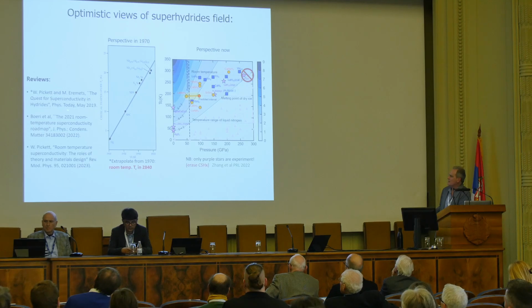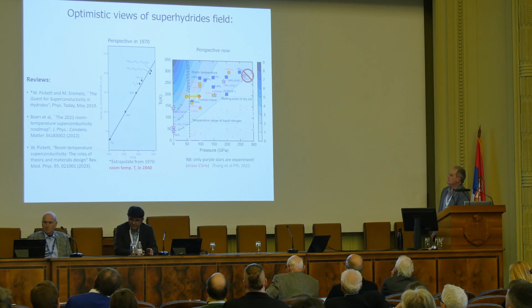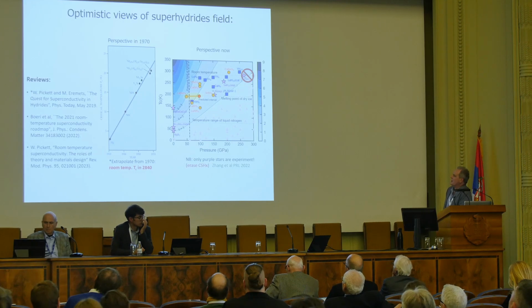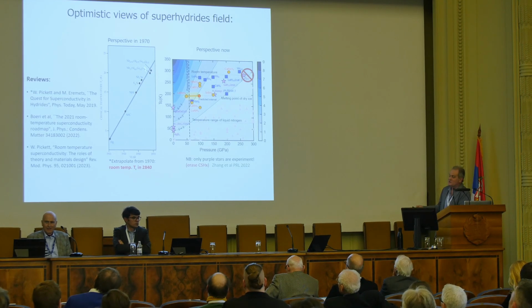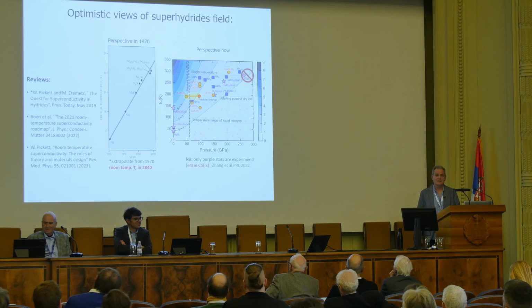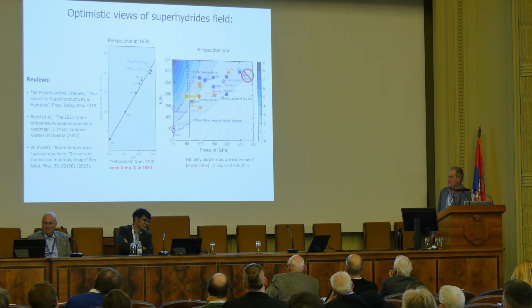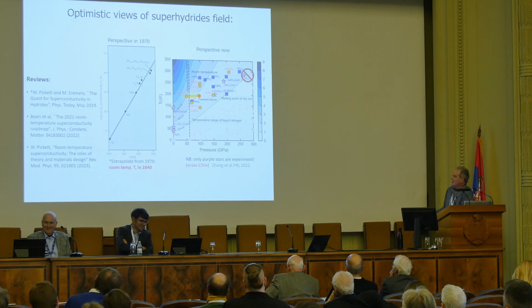plot from a paper by Warren Pickett and Mikhail Eremets. That's a nice review that they have about hydride superconductivity, where they reprinted an extrapolation, a plot made in 1970, where somebody who was rather pessimistic plotted the transition temperatures of those superconductors that had been discovered up to that time and extrapolated forward to ask when would we get a room temperature superconductor. If you do that linearly, then you're waiting for the year 2840 to get a room temperature superconductor. So we are presumably improving on that, and the improvements are described in these papers by Boeri and by another review by Warren Pickett more recently.